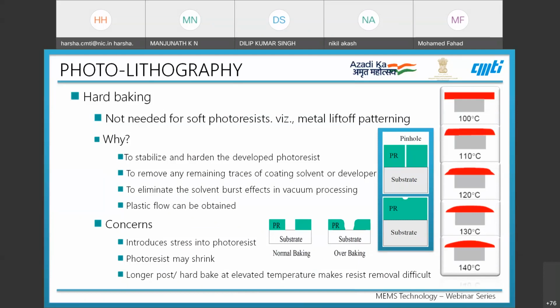This is done in order to eliminate solvent burst effects in vacuum processing and to remove the plastic flow that can result. The image on the right shows that as you increase the temperature, there is a plastic flow that is seen. At 100 degrees, the coating is proper, and at 140 degrees, it results in plastic flow.